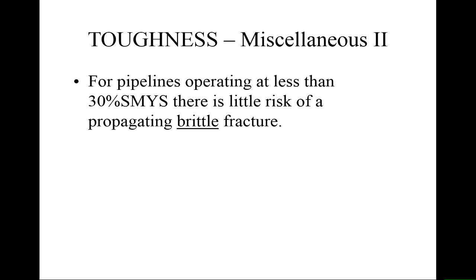Okay. Right. So how can we reduce the possibilities of fracture? Well, if the pipeline is operating at less than 30% of specified minimum yield stress, then the chances of getting a brittle fracture are virtually zero. So one way to actually deal with these toughness issues, if you suspect them, is just to downrate the pressure in the pipe. And that is often the case for assets that have been around for some time, and there's a level where you do the NDT and things like that, and then you keep these things running at a low pressure just to get as much out of them as you can and use them as backup systems, secondary pipelines and things like that, because there's no real risk of brittle fracture. Now that's for older pipe assets.